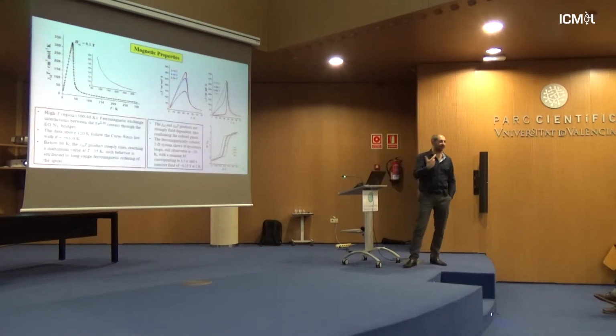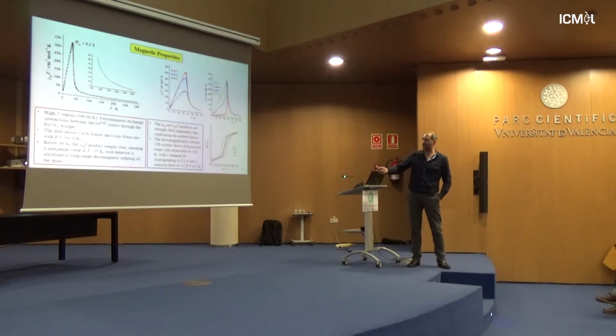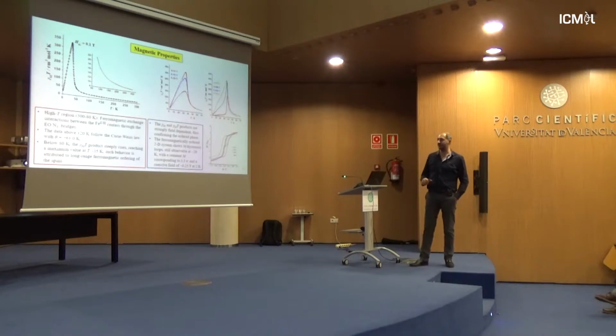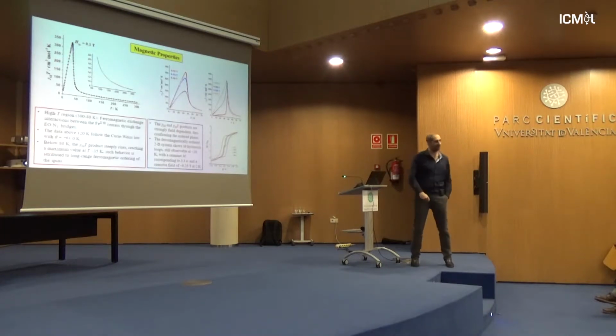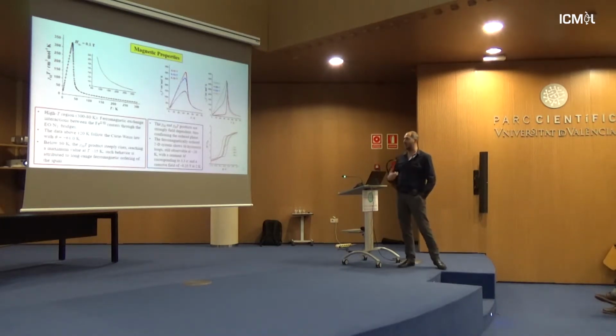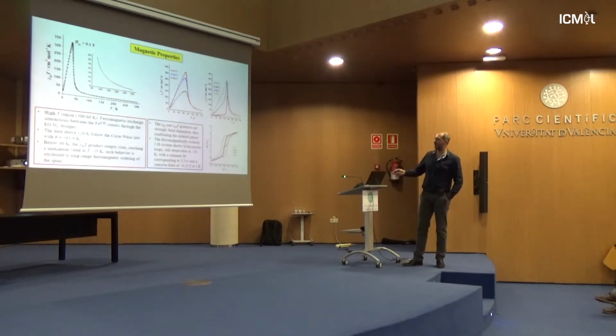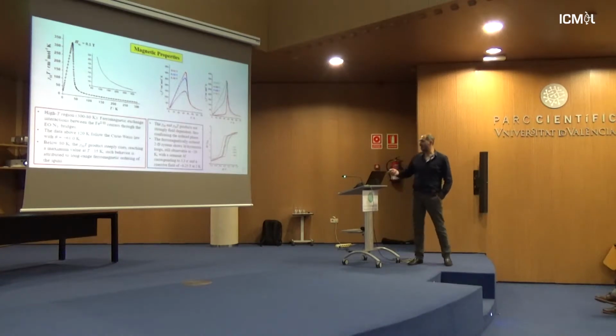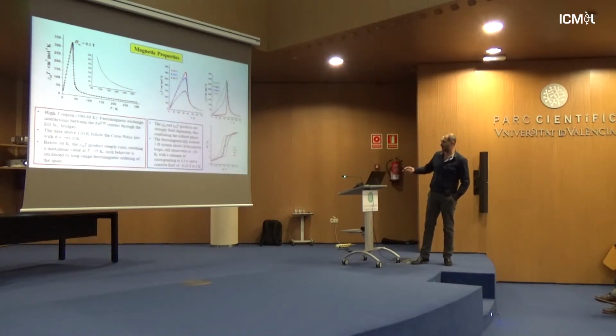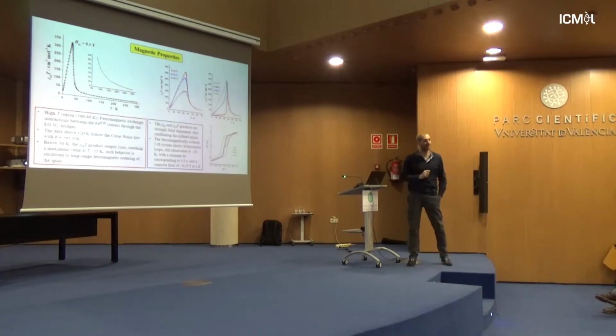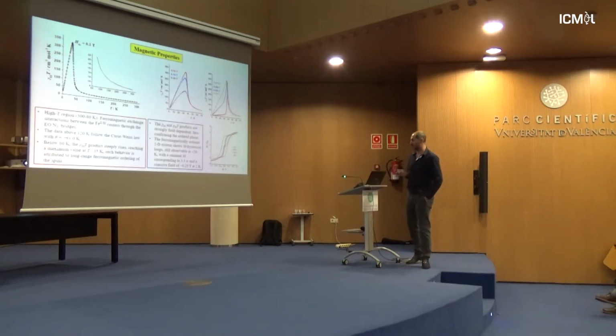The properties are not really special. We see long-range ferromagnetic ordering at low temperatures, around approximately 35 Kelvin. Above 100 Kelvin, we can still see the ferromagnetic exchange interactions between the metal centers. So it's still the end-on azides that promote ferromagnetic interactions. The ferromagnetic ordering was confirmed by susceptibility studies at different temperatures as a function of the external magnetic field. We can observe hysteresis loops at temperatures around 30 Kelvin, and the remnant magnetization corresponds to approximately 3.3 Bohr magnetons, with a coercive field of around 0.25 Tesla at 2 Kelvin, the lowest possible temperature.